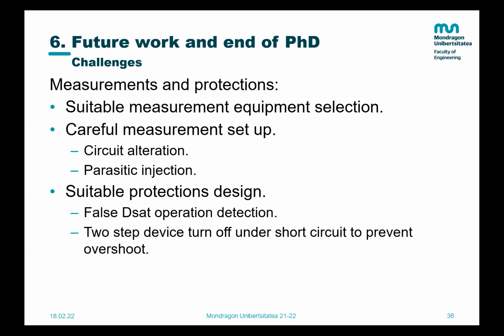And as the silicon carbide has high dv/dts and di/dts, it is very susceptible to parasitics. So you have to really be careful when you set up your measurements. You might be affecting the circuit and introducing parasitics with your measurement equipment. We suffer this too. In addition, you have to have suitable protections. So, for example, we were detecting false Dsat operation when we didn't have any short circuit because those dv/dts were affecting the sensing circuit.